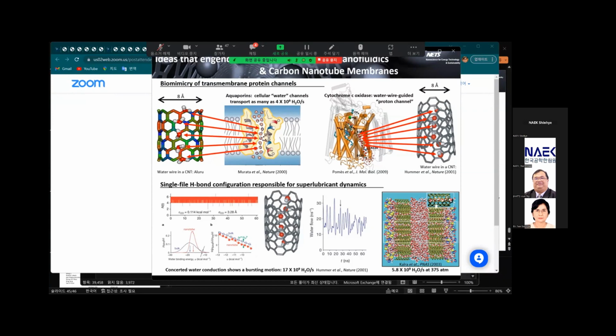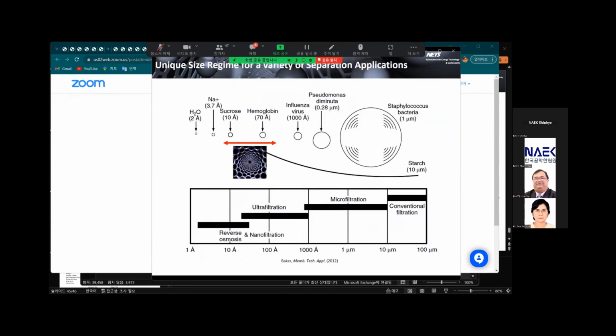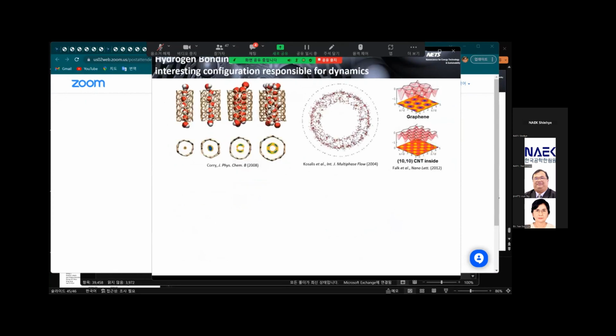Transport speed of this configuration exceeds diffusion-like transport of man-made synthetic polymer membranes, and it is often comparable to that of biochannels. In terms of water or liquid purification technology, the inner diameters of carbon nanotubes could potentially address reverse osmosis, nanofiltration, and ultrafiltration. Today, researchers understand the fast transport of water molecules confined in carbon nanotubes by both their interesting hydrogen bonding network configuration and their relatively weak interaction with the smooth hydrophobic wall.